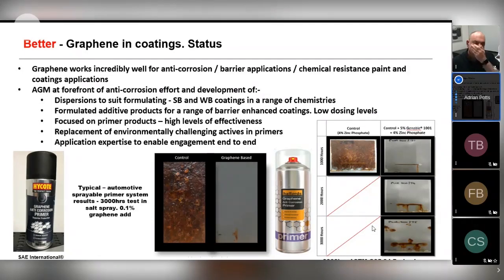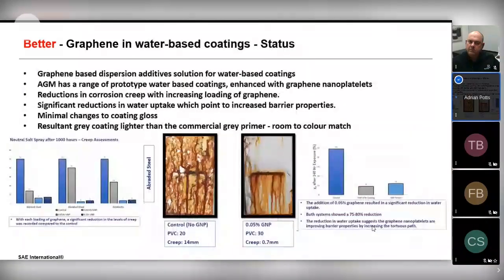Commercial products are available in aerosolized form and for spray shop applications, and then other areas for anti-corrosion performance in more elaborate systems where we're able to take the active out, so zinc and other actives, chromates and so on, to create more environmentally friendly corrosion performance products. Touching on where the industry is heading, water-based coatings are clearly the big win for the industry. We're able to add graphene very effectively to water-based coatings, and you see the little bar chart on the left-hand side here for blasted and abraded steel.